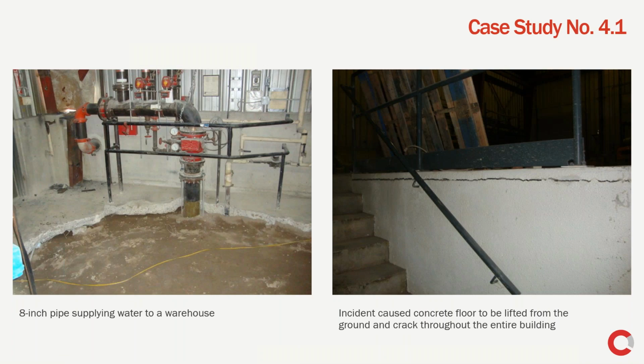Stray current corrosion can occur in underground pipes as well. If there is an electrical cable or a metal structure close by and the conditions are favorable, then the current flows from one source to another, leading to the pipe corrosion. In this particular instance, we are looking at an 8-inch diameter pipe that was associated with a warehouse. And during one night, the pipe simply exploded, causing the concrete floor to disintegrate and causing further damage throughout the building. You can see that the force of the explosion was so high that it caused concrete to separate.